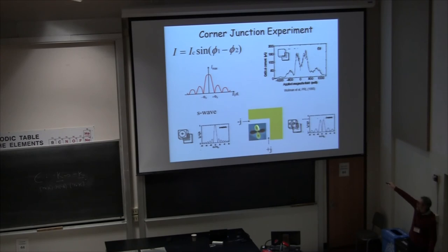only due to this material here, okay? And so this experiment was one of the first experiments to convincingly show that these high temperature cuprates are actually not S-wave superconductors, but are this kind of D-wave superconductivity.